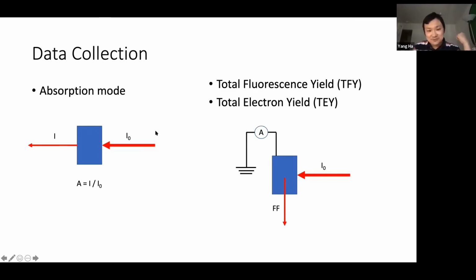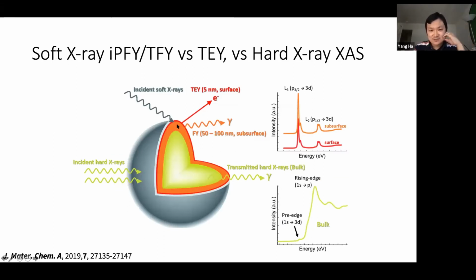So I really like this figure, which talks about the penetration depths of the different methods. So the TEY, the total electron yield, has a probe depth of about 5 nanometers, which is a pure surface sensitive technique. While the hard X-ray, we don't worry about that here because we are a soft X-ray beamline. So for the normal soft X-ray fluorescence yield, the penetration depth is about 100 nanometers. So we can call it subsurface or sub-bulk, depends on who you are talking to. And this penetration depth is enough for the particles in these battery materials.